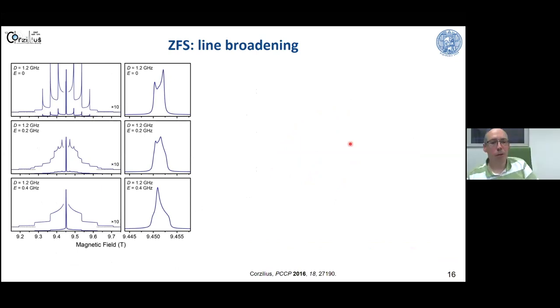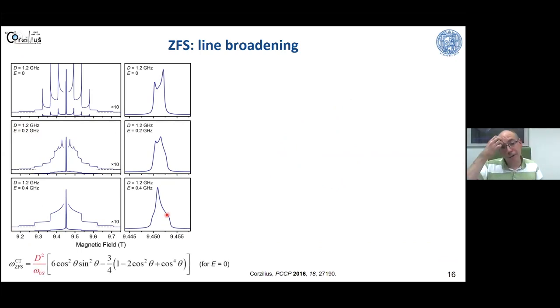All right, you can see different shapes. You can also see that this is what I've shown you before. If we now have an orthorhombic component, also a D and E parameter, then this becomes a little bit more complicated. In this purely, or ideally, orthorhombic case, it becomes again a little bit simpler. We also have an effect on the central transition. So this is only a magnification of the central transition, and you can see that you have a quite complex line shape here also. And this is due to a second order effect,